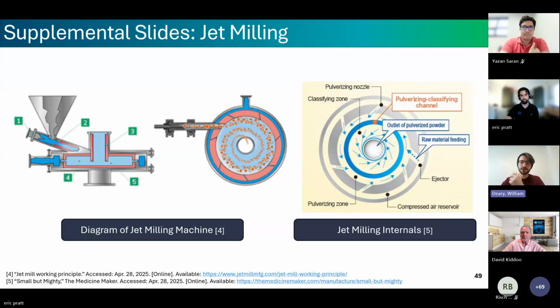Yeah, so like we said about the jet milling, I can attest it is not easy to grind XLPE to a fine particle size. I think Yazan and Eric could definitely chime in on this. We spent a lot of time trying to find a way to get that particle size down while we were at Virginia Tech. The best method that we had before jet milling was essentially a spice grinder. It was like a high power blade grinder, and even with that, Eric, do you remember how long that thing was in that grinder for? Way too long. Long enough for it to overheat, and we'd have to turn it off, let it cool down, and then start it up again. Yeah, so very difficult to get that down.